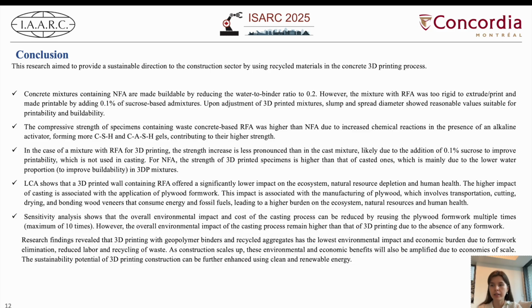Mixtures with recycled fine aggregates showed higher compressive strengths than those with natural ones, especially in casting. In 3D printing, strength was slightly lower due to the use of sucrose, but still within acceptable limits. Our life cycle assessment showed that 3D printed walls using recycled aggregates had significantly lower environmental impact, primarily because they eliminate the need for plywood formwork. Even though reusing formwork in casting can reduce impact, the 3D printing process still remains more sustainable overall.